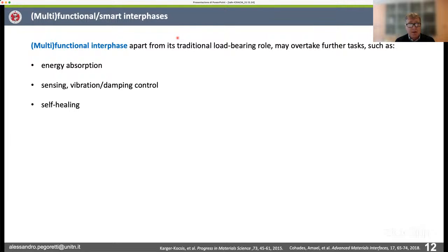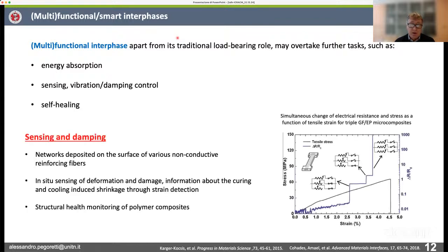I introduced this adjective because by tuning the fiber matrix interface, we also have the possibility to induce some functionality in the composite material which is not present in the uncoated or untreated fibers. For example, we can induce the capability in the composite material to sense some external stimuli, such as mechanical strain. So we can monitor the strain by changes in the electrical resistance, and this implies the composite material should be conductive, which is not always the case. If you think, for example, of epoxy glass composites, these are typically non-conductive, but they can be rendered conductive by coating the fibers in a proper way, or we can increase the damping properties of the material or reduce the damping depending on the need.